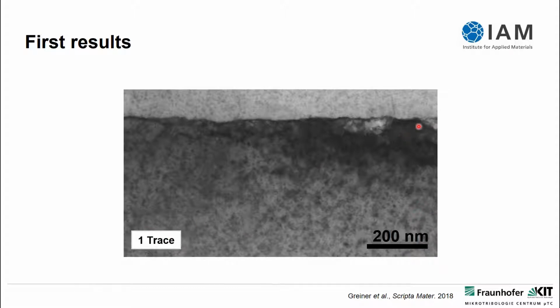You can see this discontinuity here in the microstructure—this dark contrast, which is horizontal to the sample surface. As I'm sure a lot of you have already seen in the past, so I won't go into too much detail here, we have figured out that what we see here is the self-organization of dislocations.